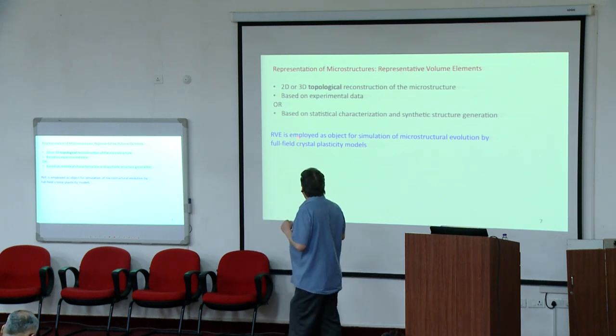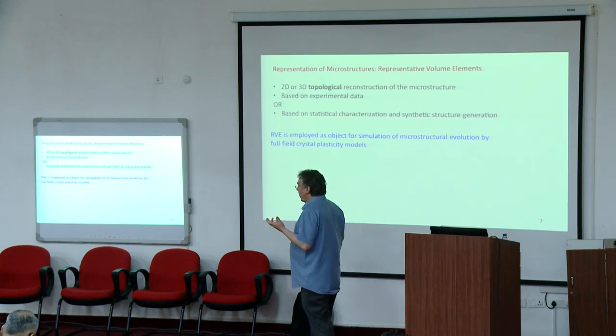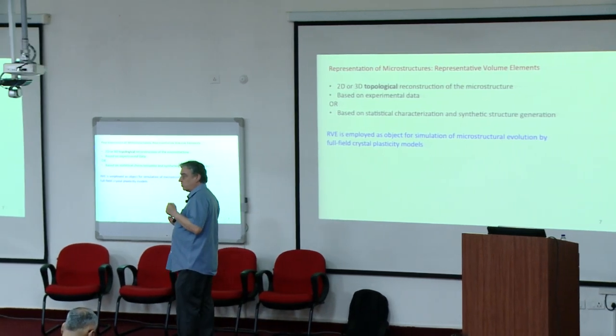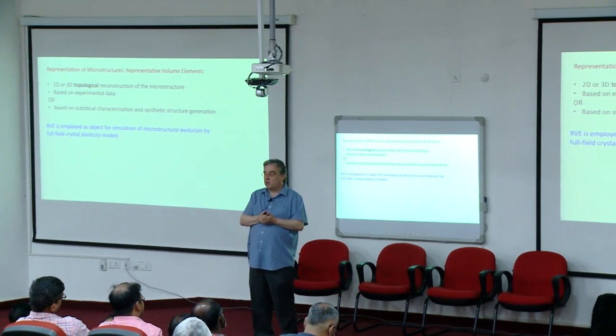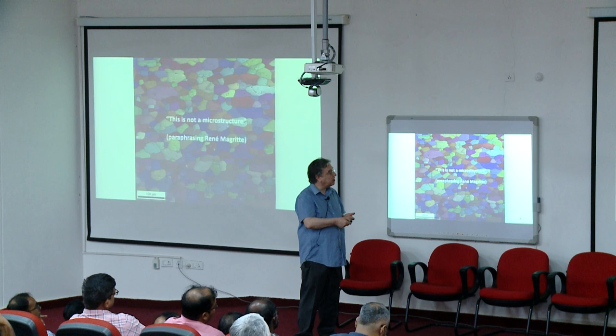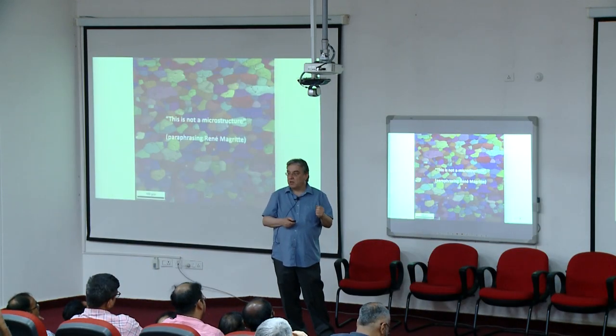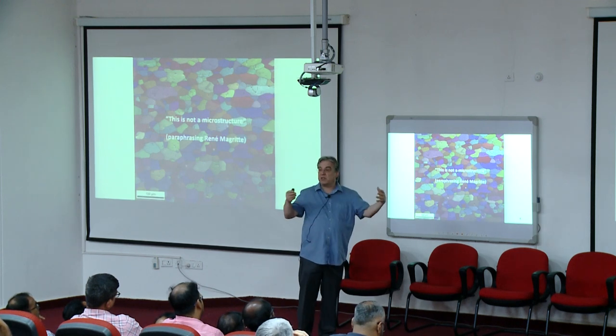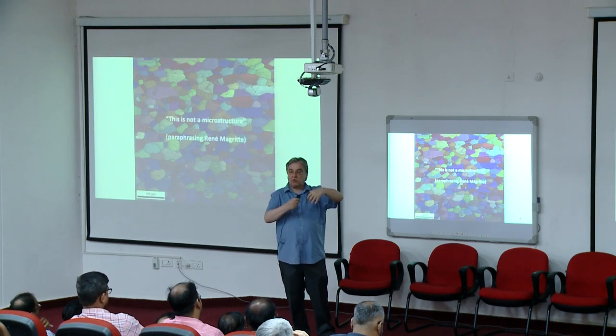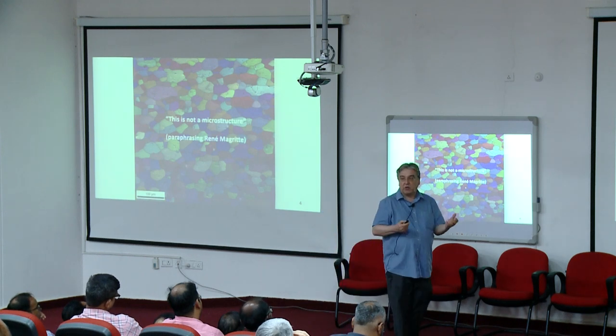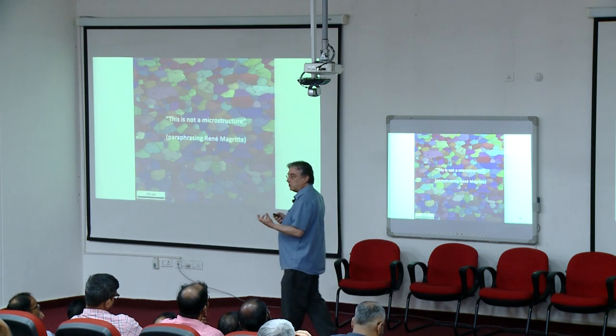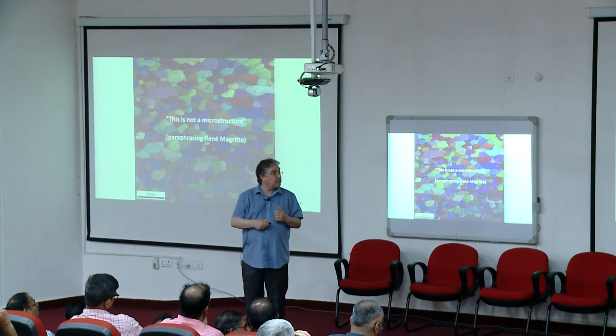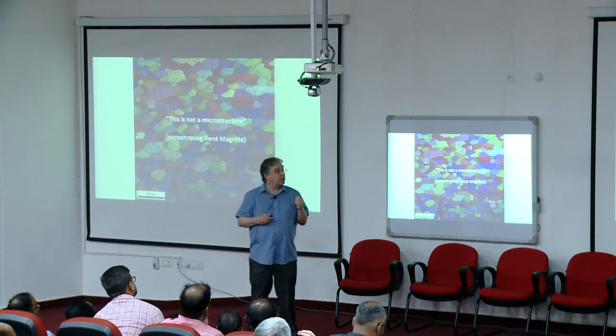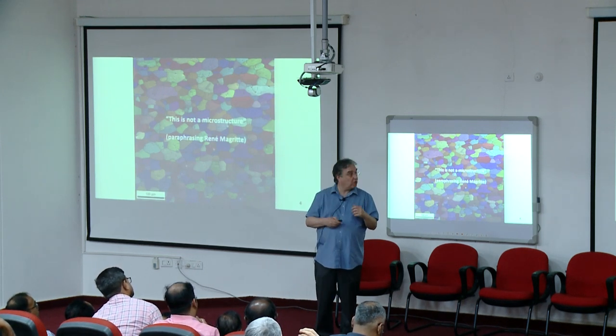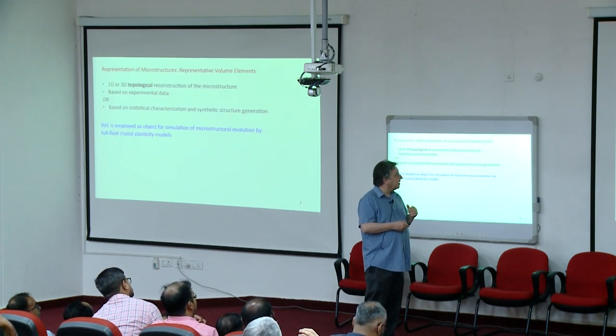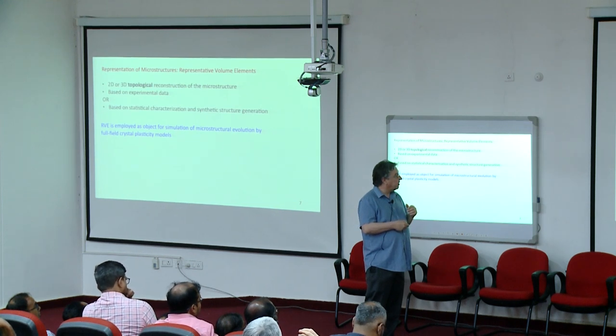Alternatively, we can also have statistical characterization and a synthetic structure generation. So you're going to construct a virtual microstructure in the computer. For example, when I had this microstructure, this is obviously an experimental measurement. So if the question would be now, how can you expand it to three dimensions? This is a two-dimensional section, how can you build up the third dimension? And you don't want to do expensive and time-consuming measurements, then you may want to develop a model that reconstructs a 3D structure based on the 2D image. That's something some people are doing. And that can then be considered as a representative volume element.